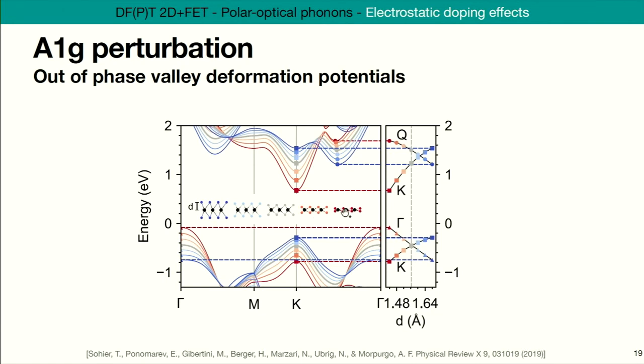And we can kind of visualize the bands moving as a function of the phonon perturbation. What's interesting here is that the different valleys move out of phase. As you remember, we said there were two valleys, and this is what we need to look at. As one goes down, the other goes up, and same on the other side. As one goes down, the other goes up. So, out of phase deformation potential. Now, this is the first step in understanding what happens.